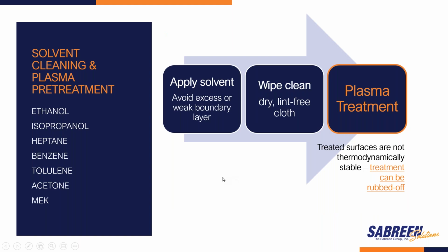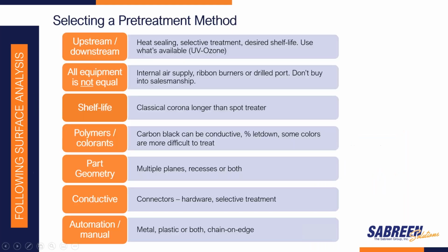One quick item about solvent cleaning, and obviously this presentation is not going into detail on this, but whether you're using an aliphatic solvent, ethanol, heptane, benzene, regardless of that, make sure that when you apply the solvent, it's not too heavy, or you're going to form a weak boundary layer. Wipe it clean and then plasma treat. Remember that treated surfaces are not thermodynamically stable, and the treatment can easily be rubbed off. So never plasma pre-treat and then try to wipe a surface clean.